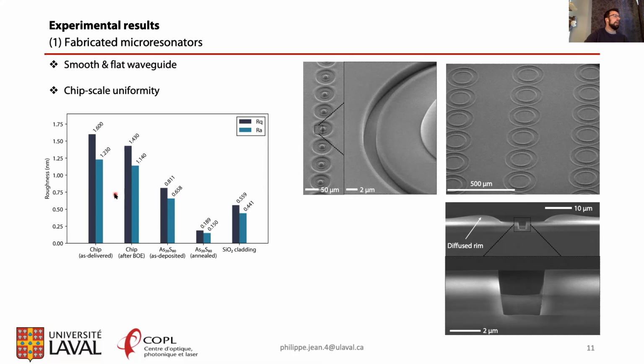Here you can see the surface roughness of the different layers of the waveguide at different stages of the fabrication process. And what you can note is that although the chalcogenide glass has a very low roughness following dewetting, the underlying silica doesn't have as good a roughness, and that's actually what we think is limiting our loss. And the SiO2 cladding is actually a very thin 50 nanometer cladding that we deposited at the end to prevent surface oxidation of the chalcogenide glass.